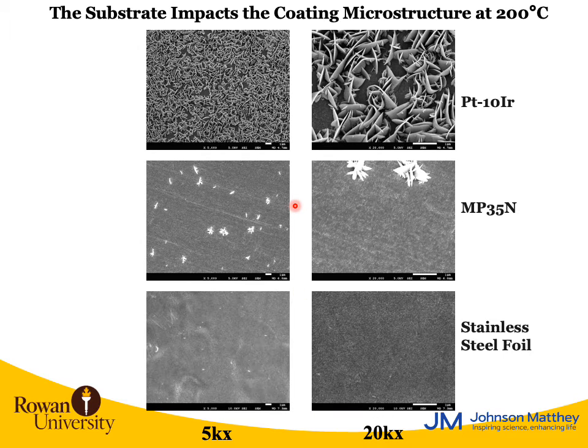It turns out that the microstructure that you see is dependent on the substrate that you look at. All three of these coatings were deposited simultaneously. The platinum 10 iridium shows lots of these platelets on the surface. MP35N shows a few that are nucleating, but not nearly the density. And then the stainless steel foil has even fewer, with the nucleation of just a few of these platelets.